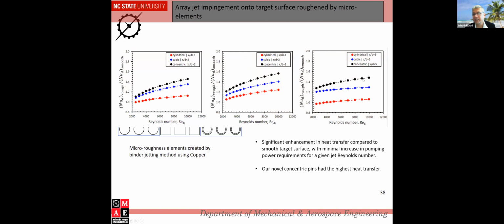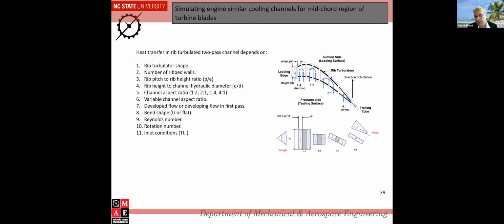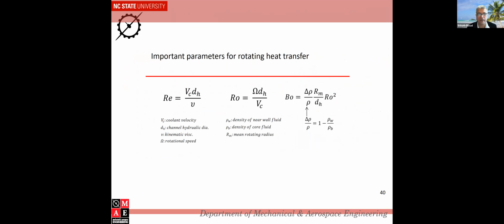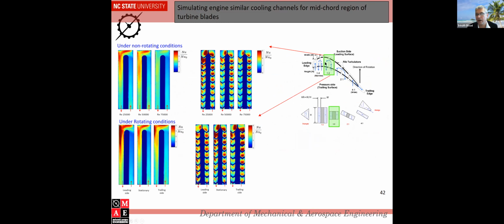So we can see that by making 3D printed surfaces, we can enhance heat transfer significantly more than traditional designs. In terms of rotation, we also do a lot of rotational heat transfer, where we look at the effect of rotation with respect to the flow velocity. We look at the buoyancy, which is the difference between wall temperature and cooling air. And we look at how we can rotate a channel like this, as I showed you in the experiment.